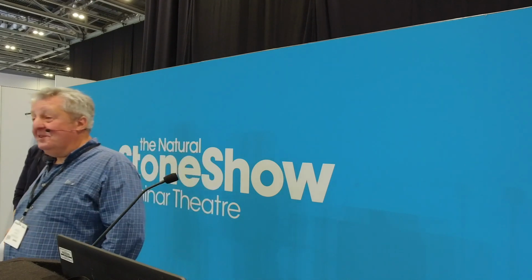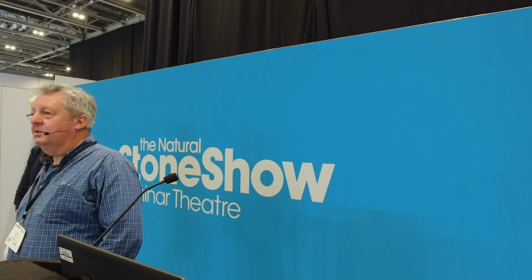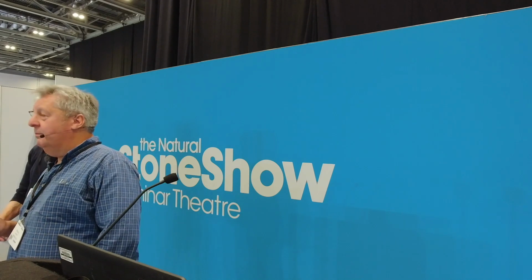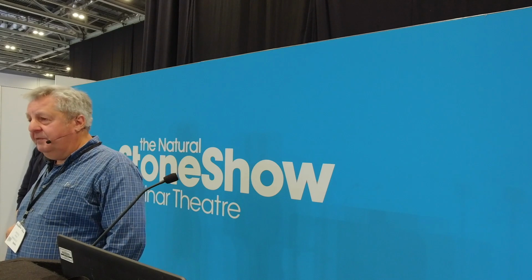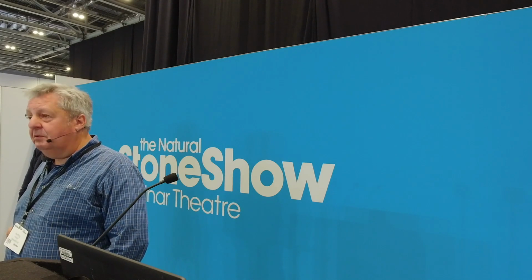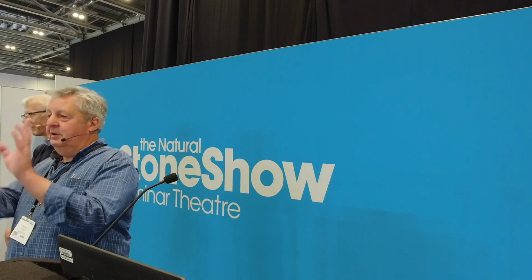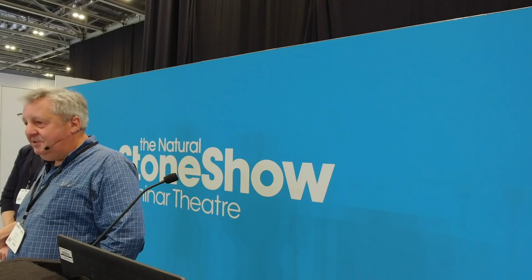Right, thank you. I like the easy questions first. The answer to that simply is no, not to that level of detail. What we were more interested in, with the standard compressive strength testing, was whether or not there was the risk of a failure within that chalk. Apart from these anastomosing veins, and they are really fine, you're talking about diameters of 0.1 to 0.5 of a millimeter, but they are packed with clay minerals, and they are quite common, and they're irregular. So it's not easy to say, as far as we know, there's one particular part of the quarry, one particular bed, where these clay veins are concentrated, so we'll avoid that and take the comparable chalk from next door. They seem to be permeating irregularly through it, so I think it's a characteristic of the rock.